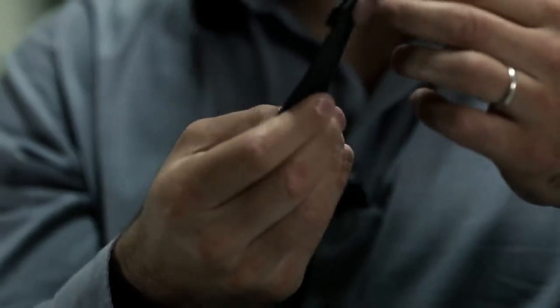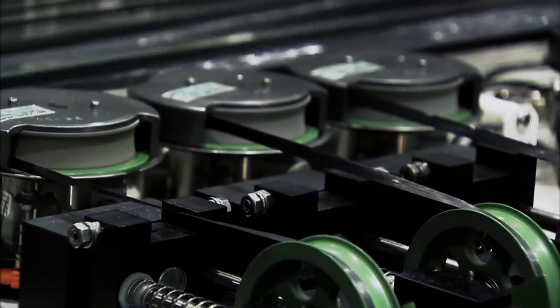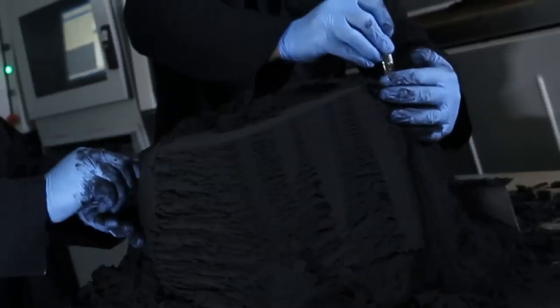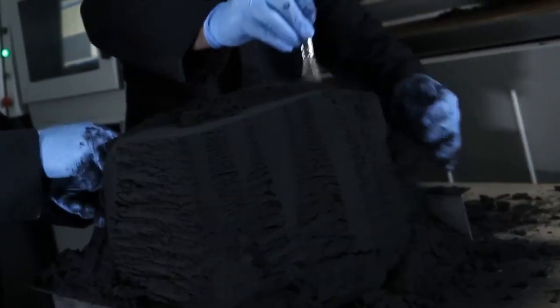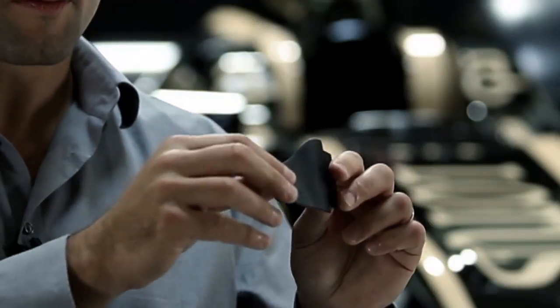This is an airflow detail on the Lotus F1 car. The challenge is how do you get reinforcement to go in all different directions? We figured out a way to take recycled carbon fiber from Boeing production and integrate that into the material such that when we spread the material into the machine, we have fibers going in all different directions. We found that we can make a better part this way using additive manufacturing, and the mechanical performance is uniform in all different directions throughout the build.